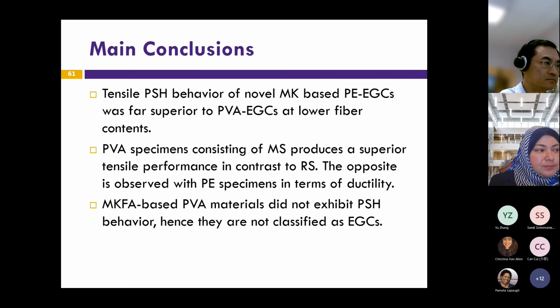So, quick conclusions. The tensile pseudo strain hardening behavior of the EGCs made with polyethylene fibers is superior to the PVA one. The PVA specimens made from microsilica sand had a superior tensile performance when compared to the river sand one. The opposite is observed in the polyethylene specimens in terms of ductility. We were not able to produce metakaolin fly ash-based materials as they did not exhibit the pseudo strain behavior that we were looking for.